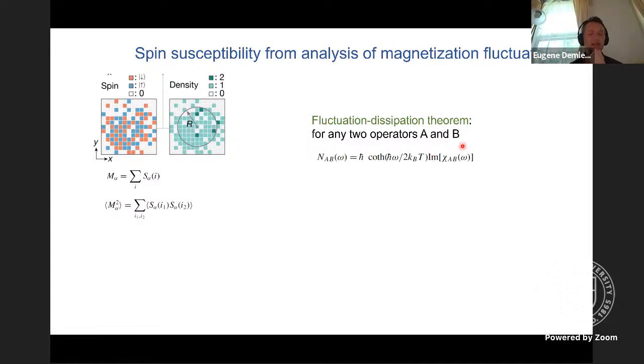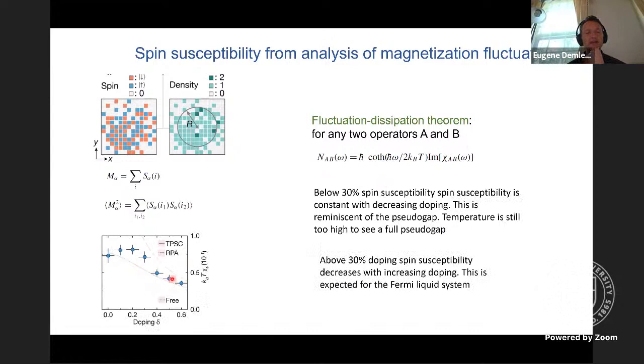It turns out that this is a telltale sign of the pseudogap regime, that it undergoes a very strong change close to half filling. And indeed, what we see in the data is that far away from half filling, by analyzing just the noise of magnetization fluctuations in a finite region, we extract the spin susceptibility, and we see that it follows the picture of weakly interacting fermions. But then it saturates, and it doesn't really show a true pseudogap, where it would have to go down. But this is a result of experiments which are not yet at the lowest possible temperature.